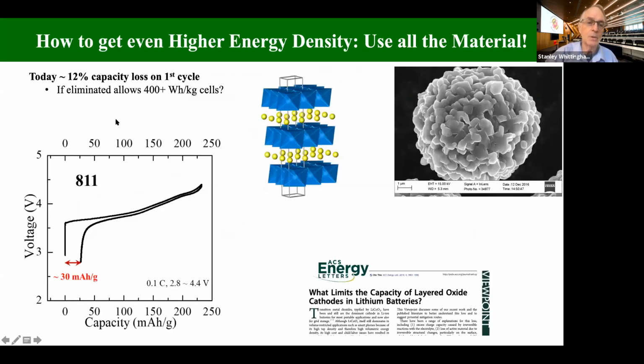But what we have to do if we want to get even higher, as I mentioned earlier, we have to use all the material. So a big challenge with all these layered oxides is what's called a first cycle loss. And this is about 10 to 15% depending on the actual cell. And I'll show you a cycling curve here. Here's the charging up to about 4.4 volts, which is typical for us. Commercial cells are about 4.2 to 4.3 volts. When you discharge it, you do not recover this last 30 milliampere hours per gram. So this is permanently lost. And this is capacity at the low voltage where the electrolyte is more stable and we should not have any problems. So it's essential that we recover it.